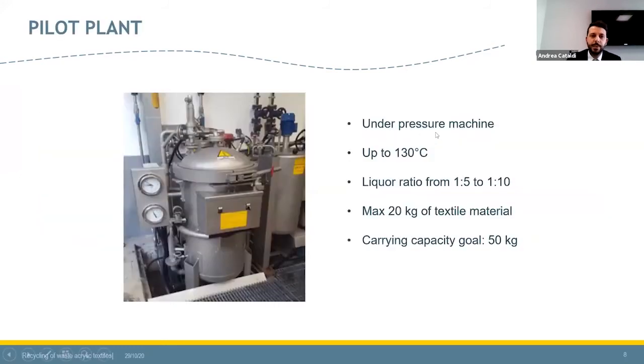Okay, and this is the pilot plant. It is an under pressure machine that can reach up to 130 degrees with a liquor ratio from 1:5 to 1:10. Maximum kg actually are 20 to treat a textile material, but the carrying capacity goal is 50 kg.